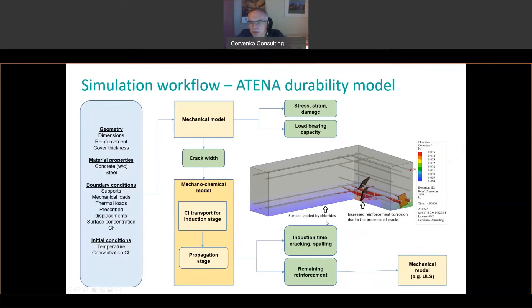Here you can see a schematic description of a small structure with reinforcement. Because we know the distance of each reinforcement bar from the surface where we apply the chloride concentration condition, we are solving a one-dimensional diffusion problem for the chlorides, which also takes into account the presence of cracks. As you can see, where there are cracks due to bending or shear load, chlorides can propagate faster — denoted by the red color indicating increased level of corrosion.